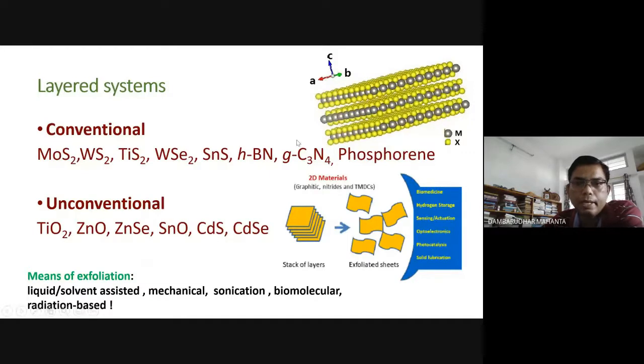Now, when you have a stack of layers, and each of these two layers are separated by van der Waals bonding, they need to be exfoliated, or peeled off the surface. For that purpose, the commonly used method is liquid solvent assisted exfoliation. You can put this stack in water and go for simple sonication, and you will find that some flakes come out of the surface. Better than water will be ethanol or methanol, in alcoholic media.